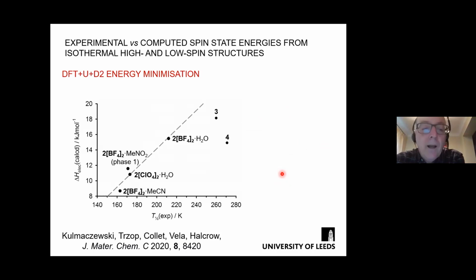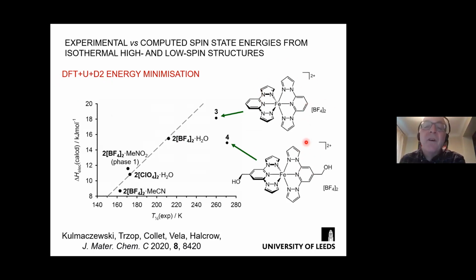Now, Sergi Vela very kindly did solid state DFT calculations for us on these compounds, plus 2 other compounds from our system where we also have photocrystallography data. So I'll show 2 graphs. These are calculated spin state energies versus experimental spin crossover temperature. And you see for the 4 complexes from this system, we have a good agreement. So the calculations are reproducing the thermal spin crossover well. These 2 compounds do not lie on the line, but these are different molecules with different crystal packing, with different lattice energies. So I think it's not surprising that these 2 don't fit on this spin state energy graph.